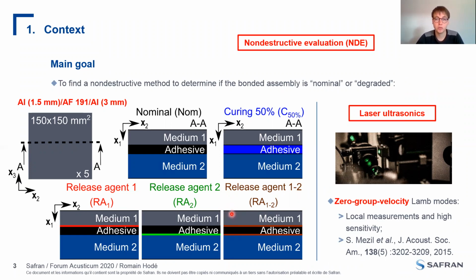So that's why we want to use the laser ultrasonic method, because this method is really interesting, notably from an industrial point of view, because it is a contactless method. And also, this method is non-destructive if we stay in the thermoelastic regime. And we want to use zero group velocity Lamb modes because they are really interesting, as I will show you in the next slide. The ZGV modes allow local measurement and really high sensitivity, as was pointed out by Sylvain Mezil in this article concerning the non-destructive evaluation of adhesive bonding, and notably concerning the study of the frequency of the ZGV modes. And in our work, we will focus on the frequency of the ZGV mode, but also the attenuation of these resonances.